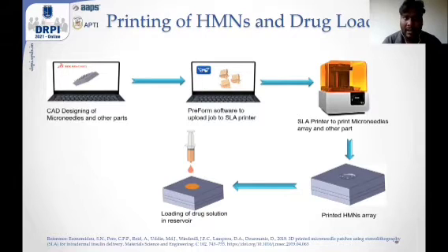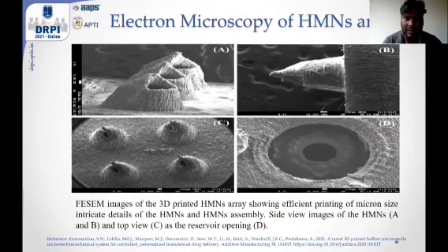Now the electron microscopy of the hollow microneedles. To detect the pore creation and the tip of the microneedles, the SEM image of the 3D printed hollow microneedles was performed as shown in the figure. There is a hollow structure, that is the pore is created at the tip of the microneedles. As shown in figure B, there is a sharp tip at the microneedles that is used for the penetration through the skin. And as shown in figure D, there is an opening in the reservoir system in which the drug solution can be loaded.